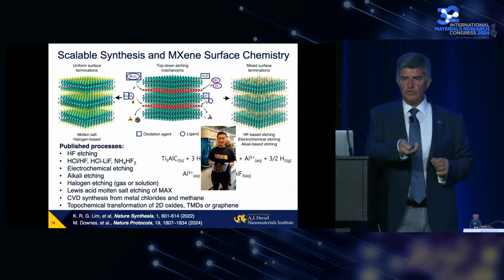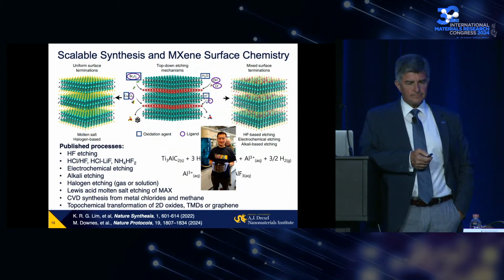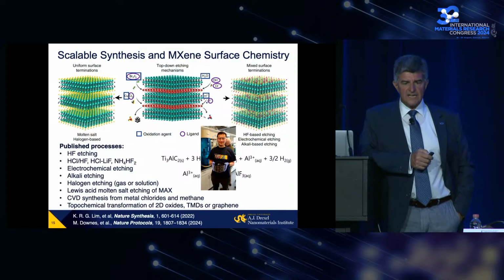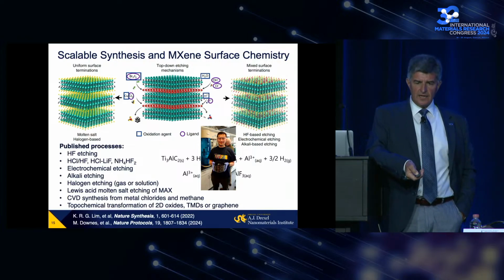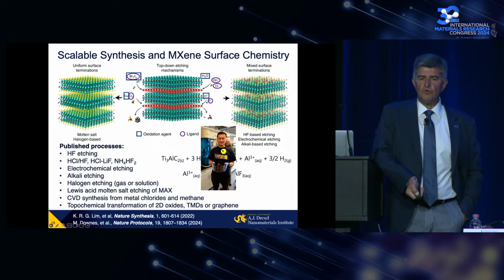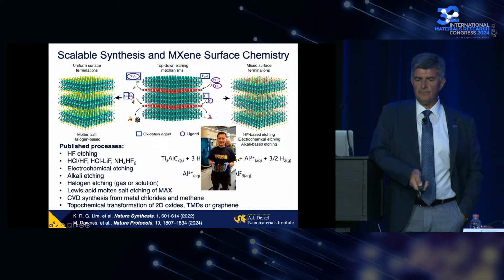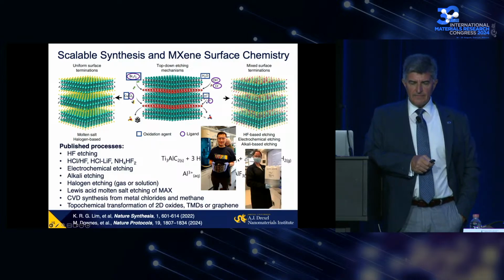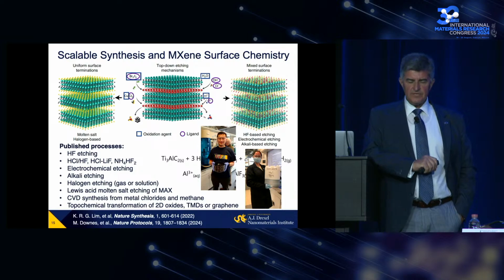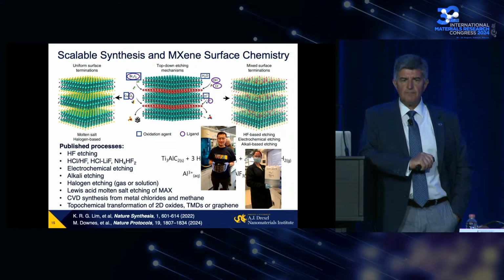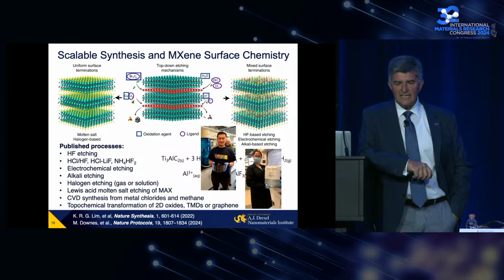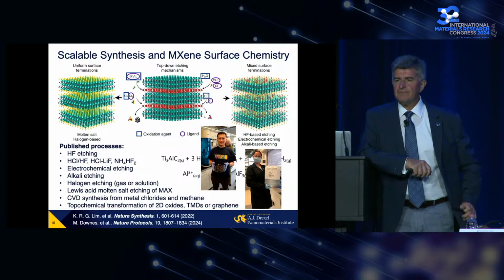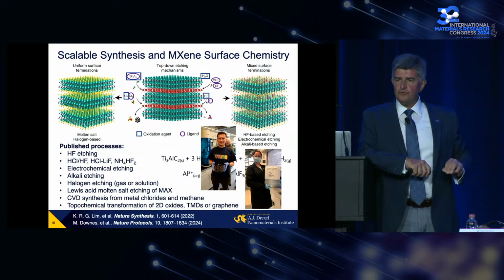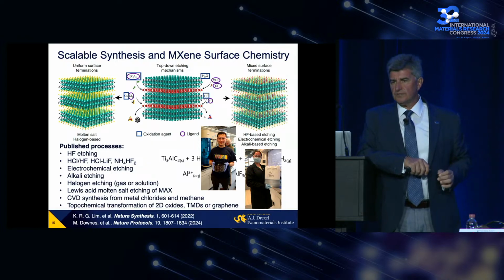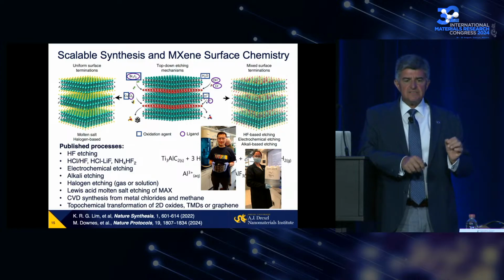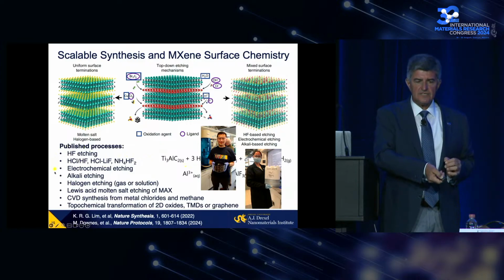My former postdoc, who just started as a professor at University of North Texas, John Wang, is holding 1 kilogram of titanium carbide MXene here. My former undergrad student, now a PhD student at the University of Chicago, Marley Downs, is holding about 8 liters of niobium carbide MXene delaminated into single to few layer flakes in water solution. We can make these materials by every single one of these methods, scalably.